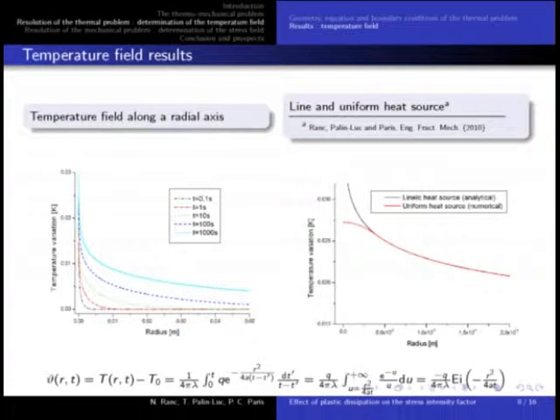What is the result? The result is the following. On the left, you have here from the crack tip, so the crack is here, the effect of the temperature. I'm sorry for the scale, which is in small letters. Here you have 0.03 degree Kelvin versus the radius. So here there is the specimen. So the analytical solution of the temperature is the following. In fact, with the exponential integral, which is this integral, you can note that the temperature variation field is proportional to Q. That's why we have plotted all the figures with a unit flux, here 1, and with lambda, which is the conductivity, and A is the diffusivity.